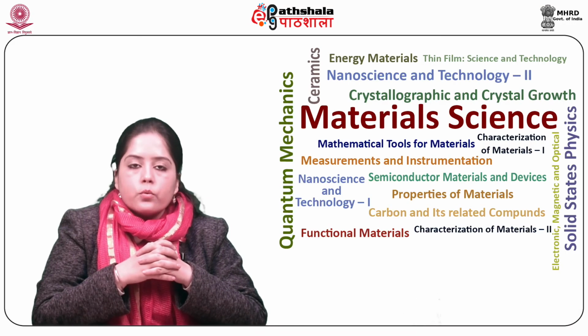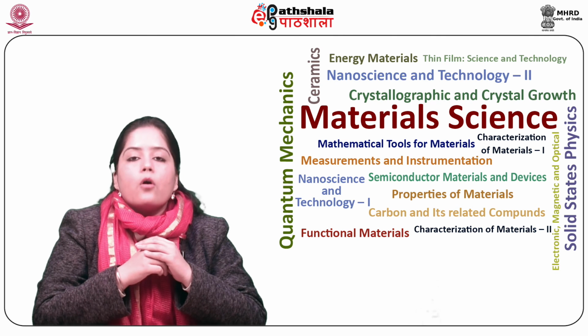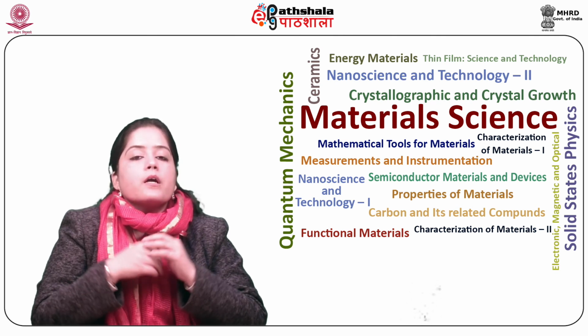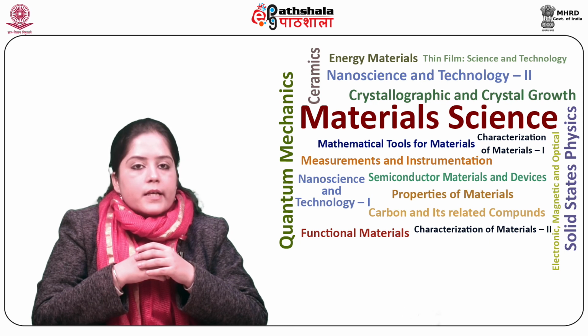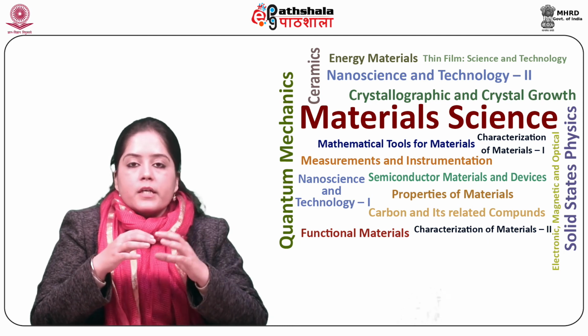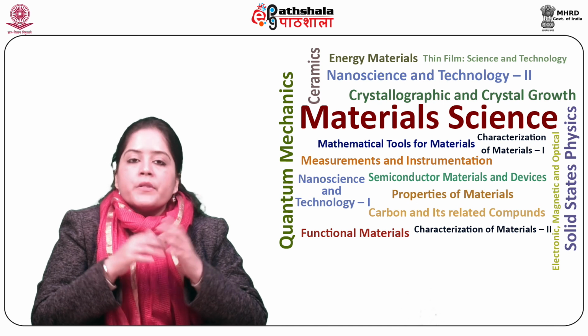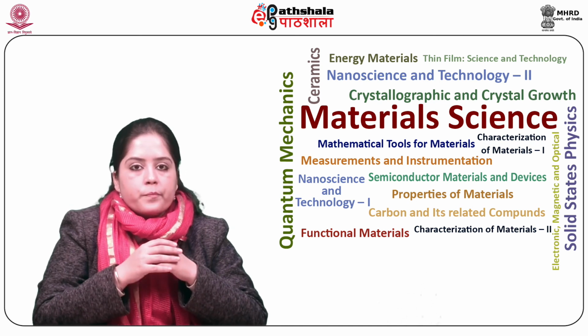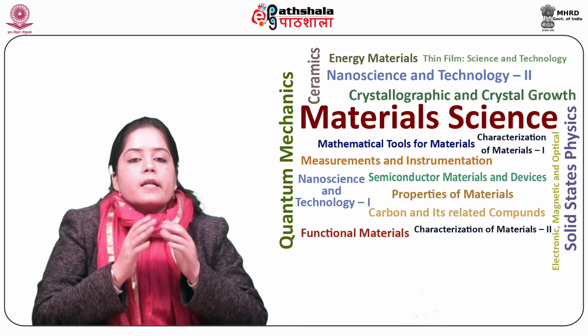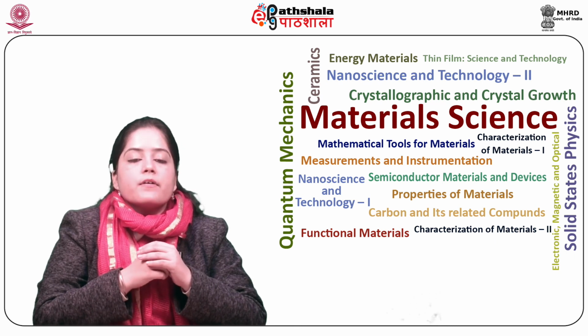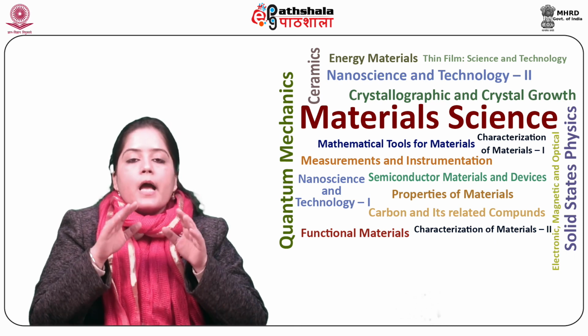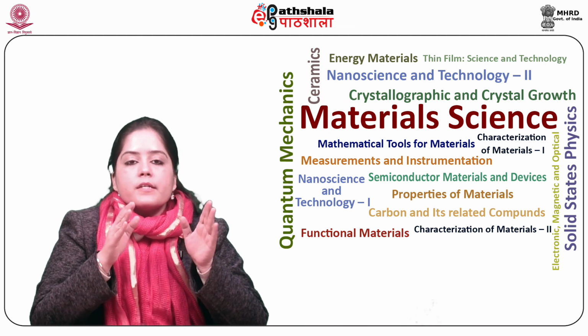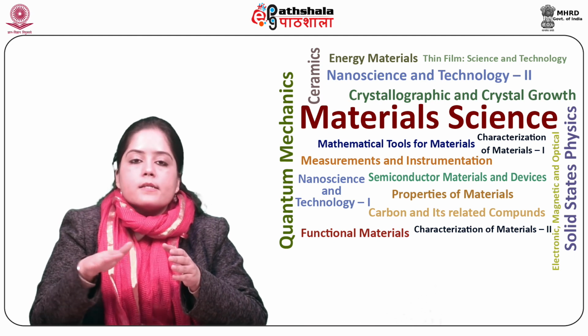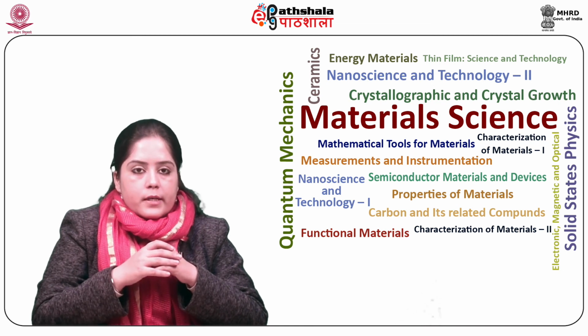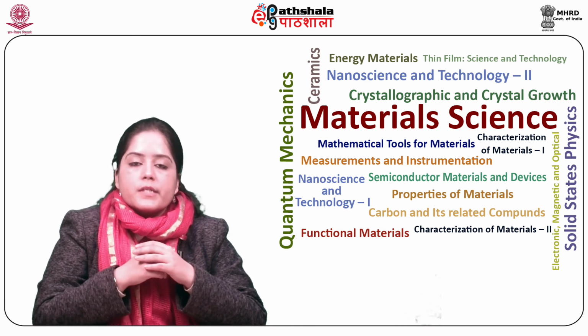Quantum wells, 2D. The effect of quantum confinement becomes apparent when the well thickness approaches the de Broglie wavelength of carriers, electrons or holes. Due to their quasi two-dimensional nature, electrons in quantum wells have a density of states as a function of energy having distinct steps versus a smooth square root dependence similar to the bulk materials.